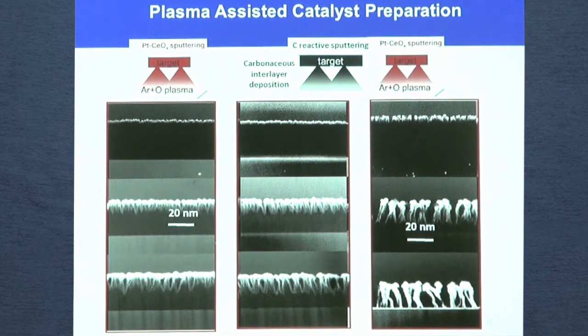And if we mix the material between this and that, we get something in between. So it shows that we are able to tune the porosity by changing not only the parameters of the deposition, but also the material properties of the carbon substrate.